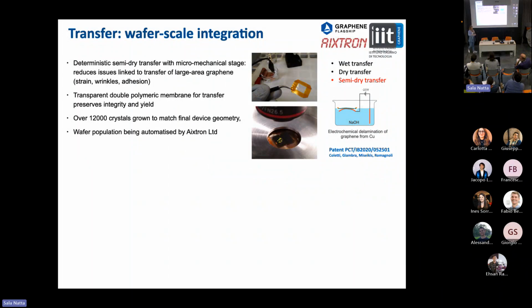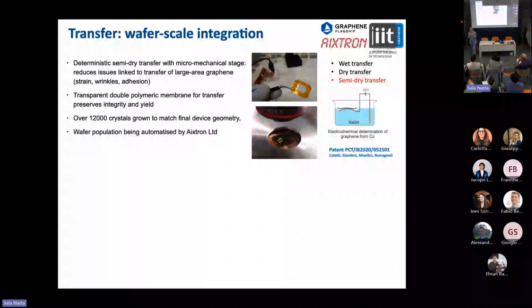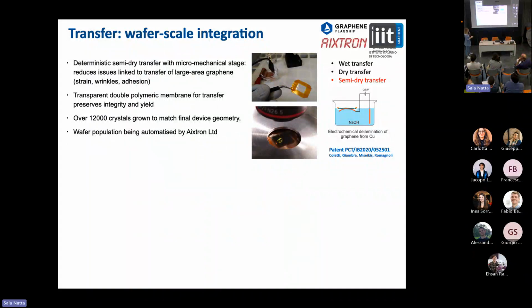The main way we do it is basically we make a frame around our copper, deposit a frame membrane on top of the graphene, and get it stuck. It's a polymer, so it actually sticks. And then we use a solution and electrochemical delamination. So we just have an electrochemical process and graphene. The old way to do this was just to immerse the copper within a copper etchant, iron chloride. I mean, there are different ways to do this.